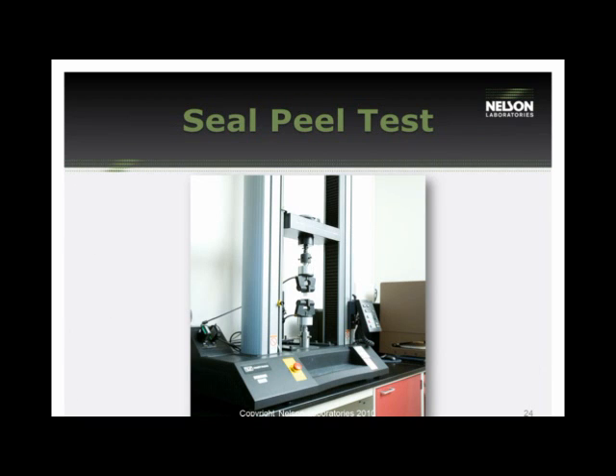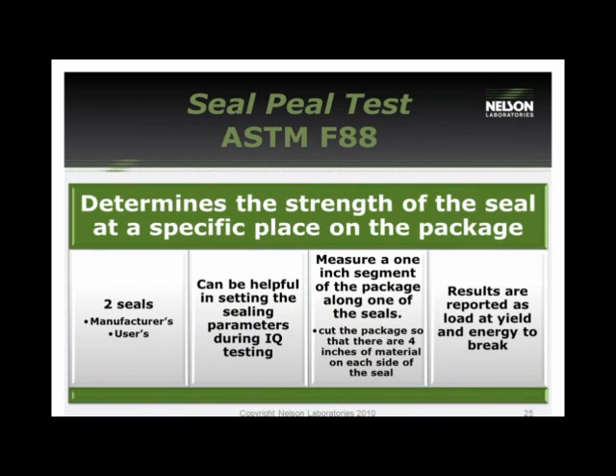Okay, so we're going to get into the seal peel test. The seal peel test is regulated by ASTM F88, and it determines the strength of the seal at a specific place on the packages. We recommend that you perform two seals. You want to use the manufacturers and the users. Additionally, it can be used for setting your sealing parameters as part of an IQ test.